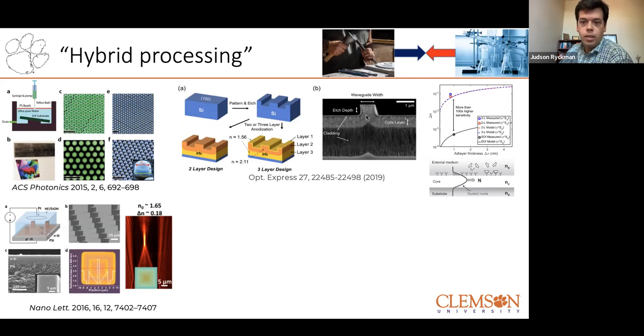We make optical waveguides, in this case, a rib waveguide, which is now porous. So that means analytes can infiltrate inside of the waveguide rather than being limited to evanescent interaction that you would have in a conventional platform. So this is one example. And as we characterize the sensitivity of this type of structure, if you look at its response to small molecules, you'll see that the porous structure has about 2 orders of magnitude larger response than the evanescent or non-porous waveguide. So we really boost the sensitivity, and we think this could allow us to drive the limit of detection down much lower than more conventional platforms.